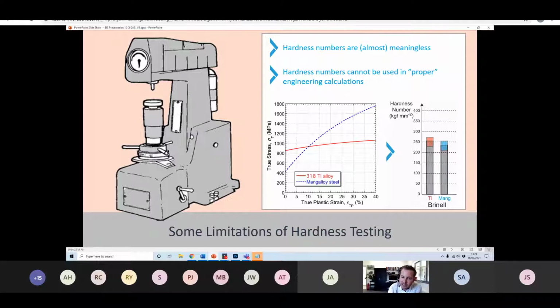And therefore you couldn't actually distinguish these two materials on the basis of their hardness numbers alone. And you'd be ill-advised, in fact, to design something thinking that the yield stress might be close to 800 megapascals off the back of a hardness test when it could in fact be closer to 400 megapascals. And the reason that I raise that is because some people try and equate a hardness number to a yield stress by invoking a factor of 3 between those values. Okay, so it's actually very dangerous to do that and can lead to all sorts of problems. So while the test is simple, quick and easy, the problem is that the data that you get is to some degree also meaningless. That's maybe slightly too strong.